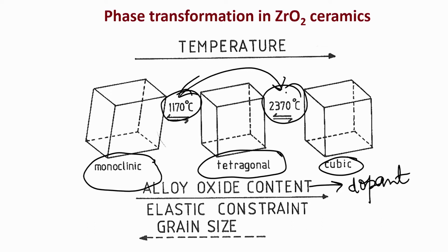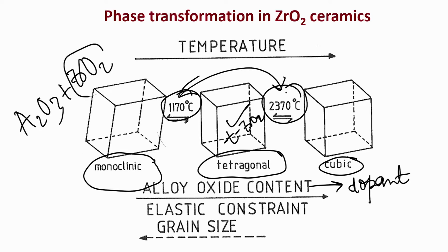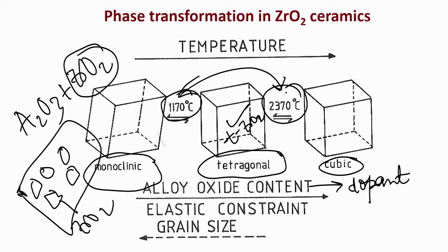So, if your dopant content increases, it means that this particular tetragonal phase, what we call T zirconia phase, is stable at room temperature. And if the elastic constraint in the matrix also increases, for example, if you add zirconia to an alumina matrix. So, you have pure alumina and then you add a little bit of zirconia in the alumina matrix. These are the zirconia particles. But these zirconia particles are constrained in an alumina matrix; alumina has an elastic modulus of 390 gigapascal, whereas zirconia has an elastic modulus of 210 gigapascal.